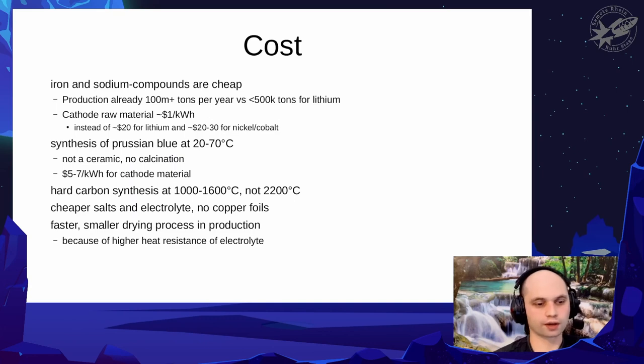And that's quite possible, especially because the salts that you need and the electrolyte are much cheaper. And you don't need copper for the foils. And because the electrolyte is much more resistant to high temperatures, you can use higher temperatures for the drying process after you have coated the foils with your cathode and your anode material, and then it's wet and you have to dry it out. You do that in long ovens, and the higher the temperature you can use, the shorter the time required, and the shorter and smaller your ovens can be.